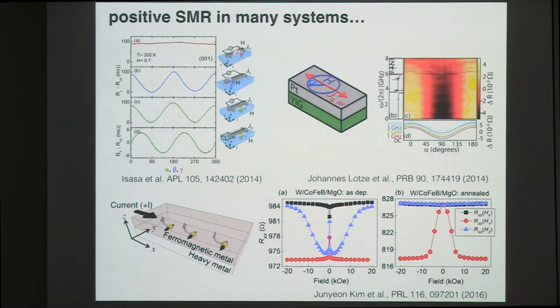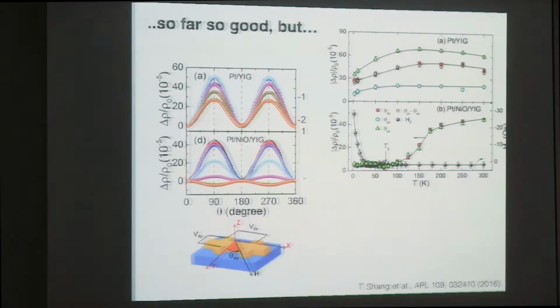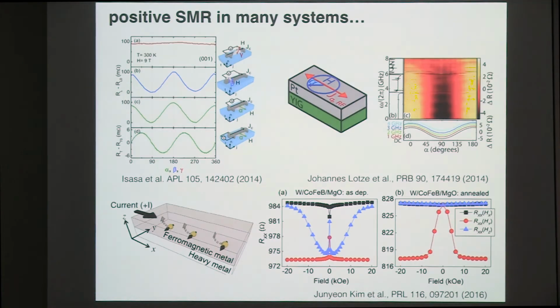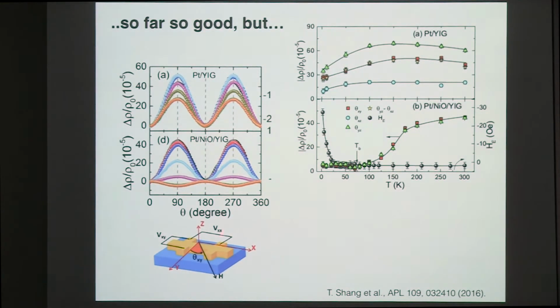So actually, this kind of positive SMR has been confirmed in more than 100 reports. I just gave some examples here. Also, I think this one is from Felix. But sometimes we noticed some very strange reports. These guys measured this platinum nickel oxide YIG, which we are very familiar with. They compare the SMR between standard bilayer and trilayer, and they find that for the bilayer, everything is expected. It shows a very mild temperature dependence, so nothing really interesting. But they show that in this trilayer device, the MR is positive at room temperature, but it goes down all the way with the temperature, and actually has a sign change here.